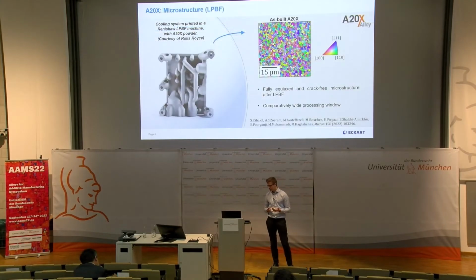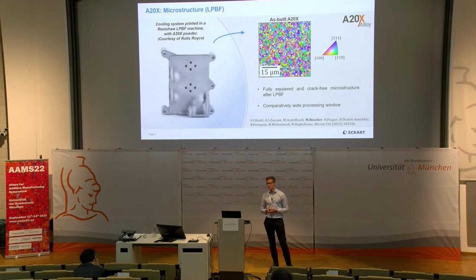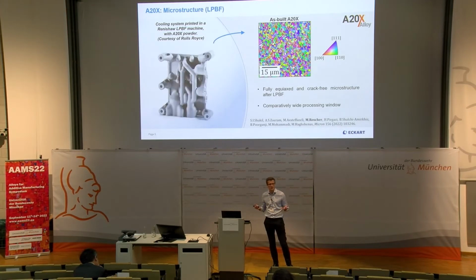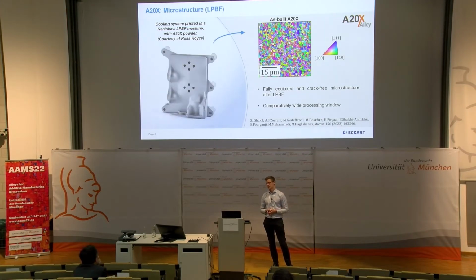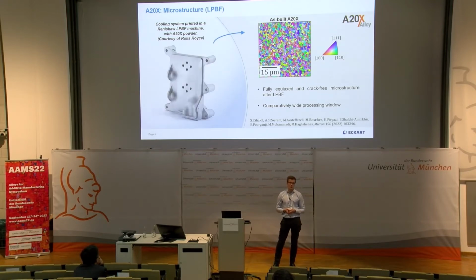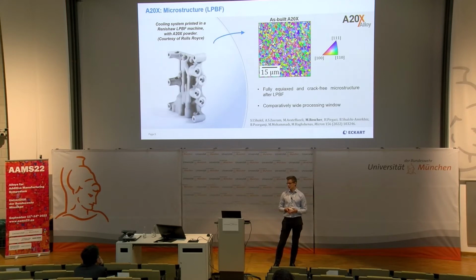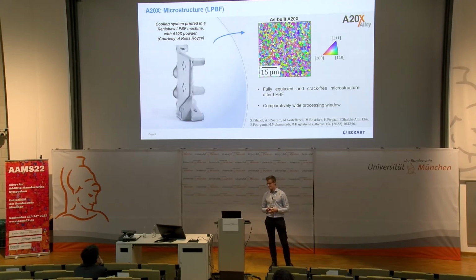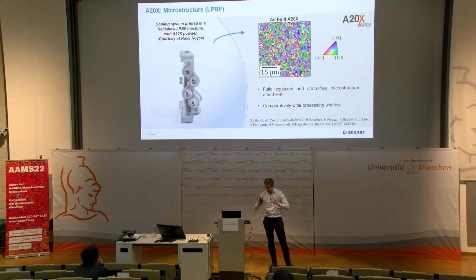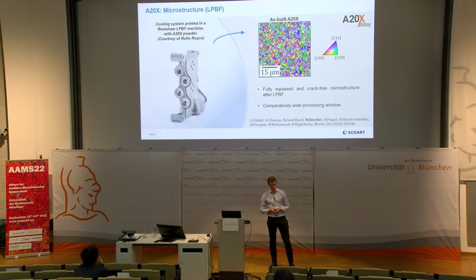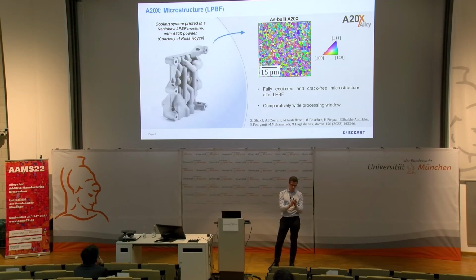So one of the key features that enables the good processability is the high degree of grain refinement that is achieved during solidification. This is related to the titanium diboride addition and ultimately results in the suppression of cracks. So in this particular example, the average grain size is about 1.5 microns in the as-built A20X sample. During heat treatment, which is typically employed in actual applications, the average grain size slightly increases but stays within the single micron region.